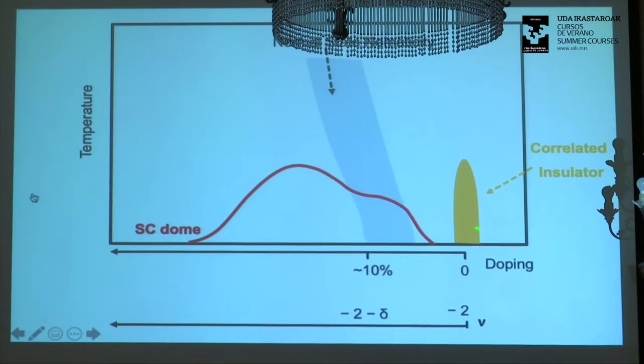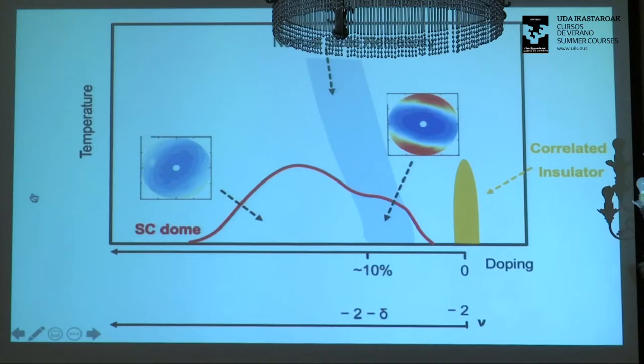Separately, everywhere in the superconducting dome, you have nematicity in the superconducting state. If you look in the overdoped region here, your nematic axis is in some direction. When you tune your density such that you go to the region where you have normal state nematicity, the axis, your nematic director for the superconductivity, flips. So what that means is the following. Your superconducting state is nematic. The direction that it chooses for nematicity, there is probably some weak strain that is ultimately pinning it in some direction. Otherwise, it would be freely rotating, even though it would be a nematic director. So there's probably some little something structural.